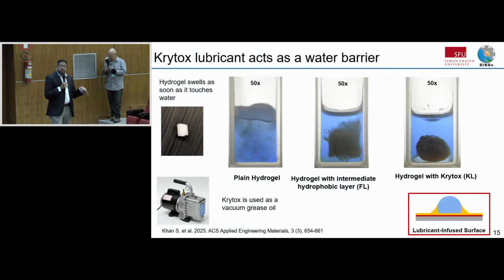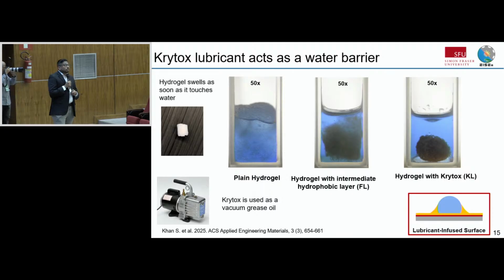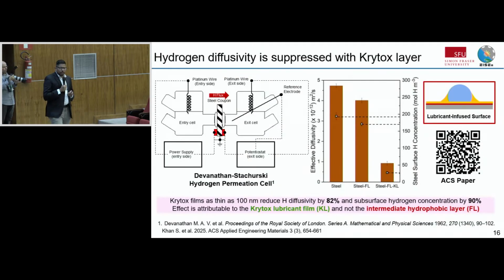The Krytox layer, which we call KL, that barrier layer, it's stopping the corrosive liquid from going inside. So really that video was to show you that these liquid layers can be as thin as 60 nanometers. It's a thin layer of oil. We showed through rigorous electrochemical experiments that it can slash the hydrogen diffusivity by almost an order of magnitude.